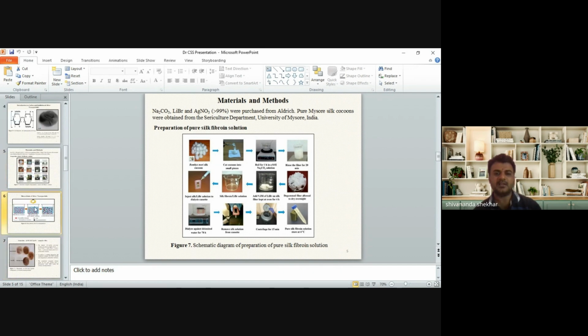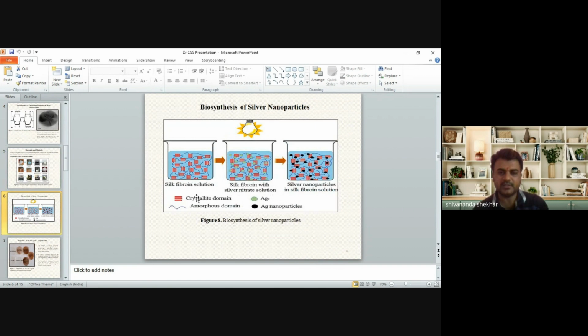Then, whatever pure silk fibroin solution we get, this is a schematic representation. We added different ratios of silver nitrate, that is raw silver nitrate, to the silk fibroin solution. So this is purely a biosynthesis approach. Here we have not used any kind of reducing agent. The silk itself acts as a good biotemplate, and it is able to reduce the silver ions into silver nanoparticles. So this is the schematic presentation. Here we have exposed this solution to incandescent light in order to speed up the reaction. Later, at this particular stage, we obtained the colloidal silver nanoparticles present in the silk fibroin solution.